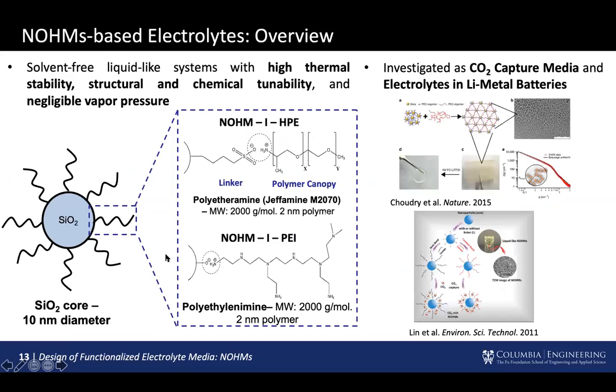So NOHMs are nanoparticle organic hybrid materials. They're essentially polymers tethered onto nanoparticles. And we've used a couple of different types of polymers for this. The main ones I've looked at are polyetheramine, which has the structure shown here. So we see it has this ether group functionality, as well as PEI that is constituted by amines and is formed by polyethylenimine. So these are the main types of polymers, but these materials are highly tunable.